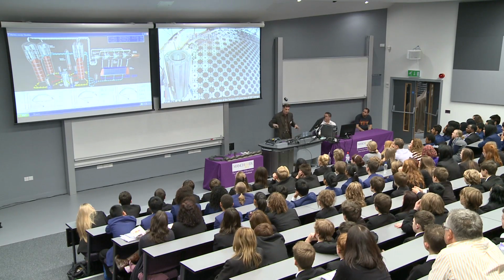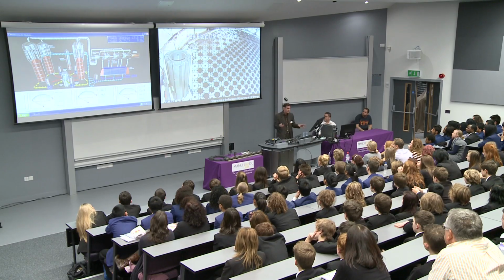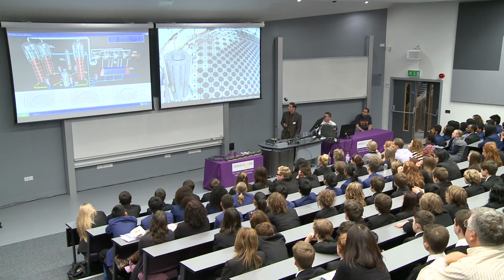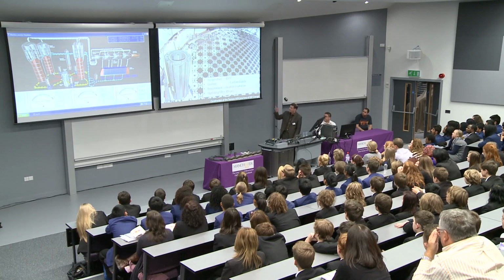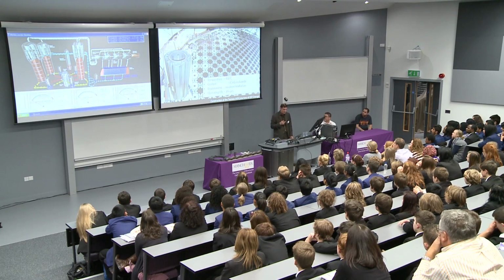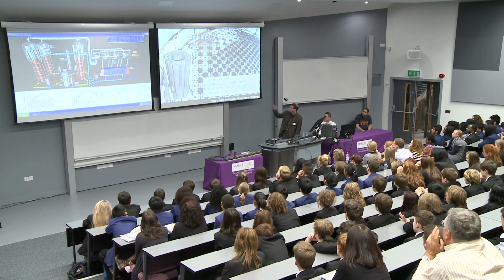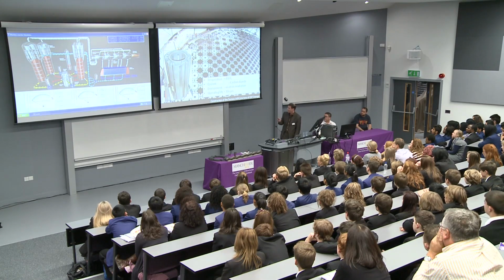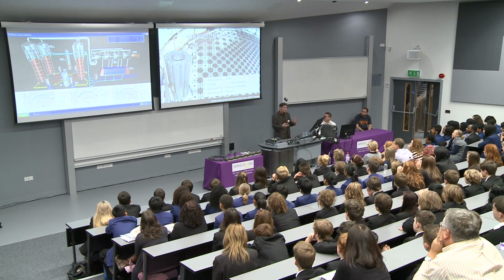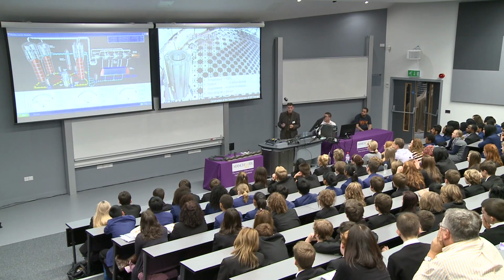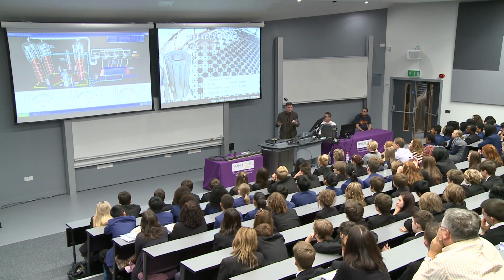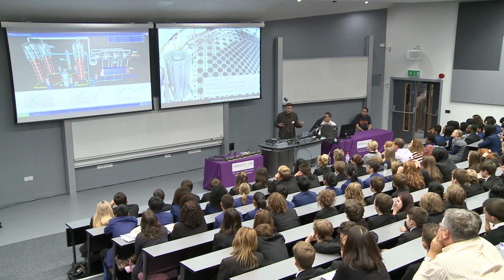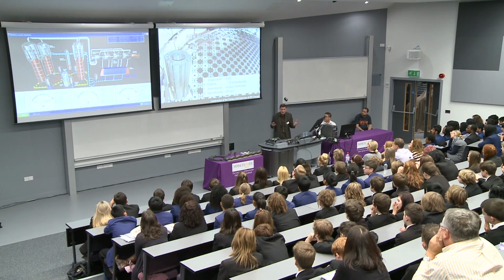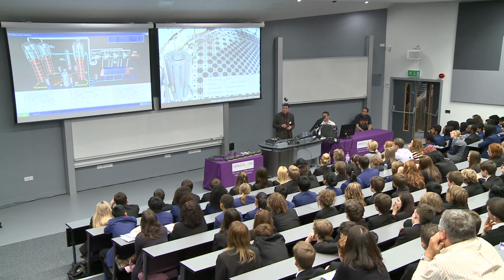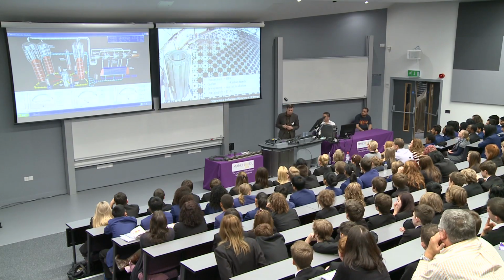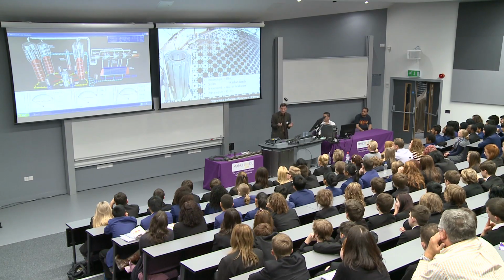And that core will operate for around about 30 years or maybe a little bit longer if we can keep the thing going safely. This operates at about 450 degrees centigrade. As I said, the coolant is carbon dioxide, but also you've got the nuclear reaction going on within the core, and so there are neutrons which are bombarding this core the whole time during the operation, and those neutrons actually change the properties of the material, and we're looking to operate this for at least 30 years.